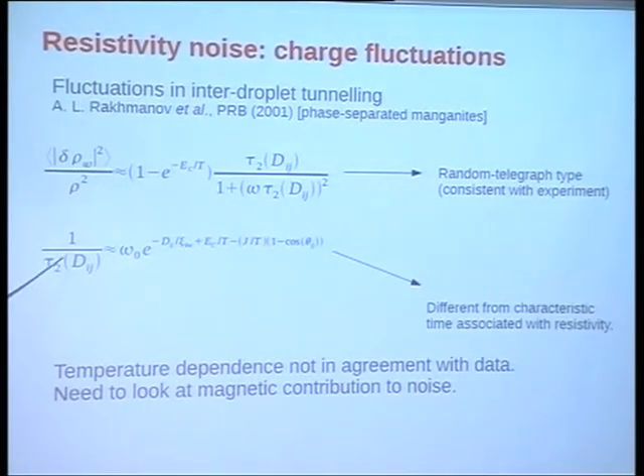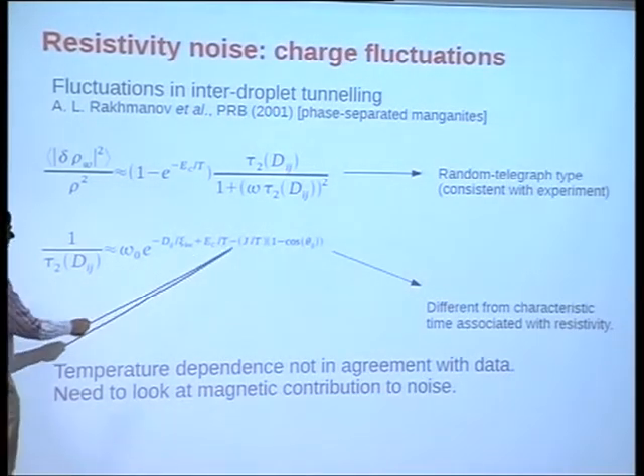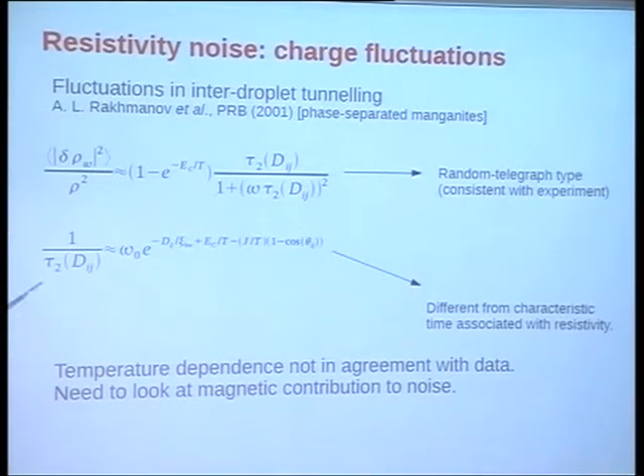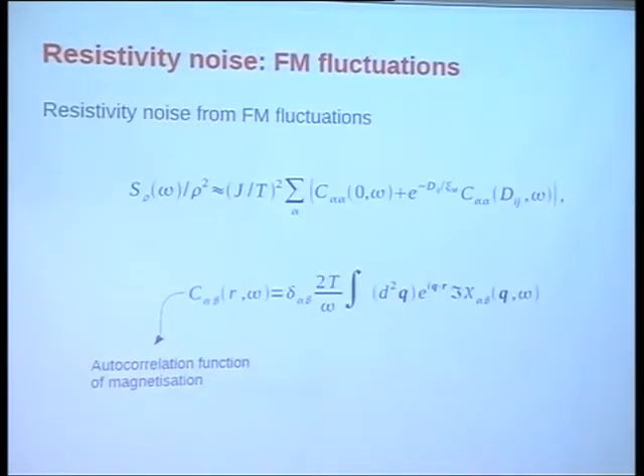Notice that this scattering rate is not really the function we used for resistivity. In fact, there was a sign difference here. Nevertheless, it depends on the same kind of quantities. But unfortunately, we find that this doesn't explain the data, meaning we cannot find any reasonable values of E_C and J to account for the data. We can take unphysical values and sometimes manage to fit. So we started looking for resistivity noise due to ferromagnetic fluctuations.